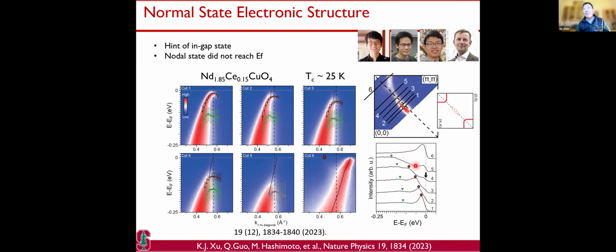Okay. Also, pay attention that you see states at 5. You see where my cursor is. Okay. Now this is well inside this magnetic gap, the anti-ferromagnetic gap. Now, seeing states inside the gap is not that surprising. In a gapped system, you often have impurities and all that. The question is, are those interesting states?